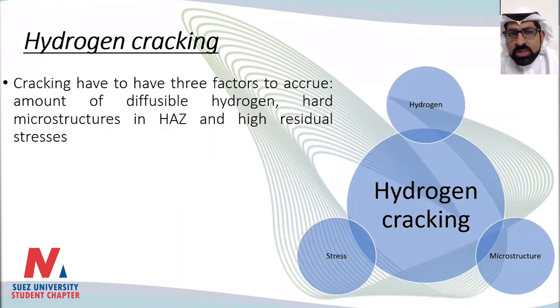Next slide, please. Hydrogen cracking needs three things. It needs a lot of hydrogen, which we already have because we are in water. We need a brittle microstructure, which we already have because we are welding and quenching at the same time, so you are welding and fast cooling at the same time. And also residual stress, which we already have by creating the weld. So we have all three parts that make hydrogen cracking easy.